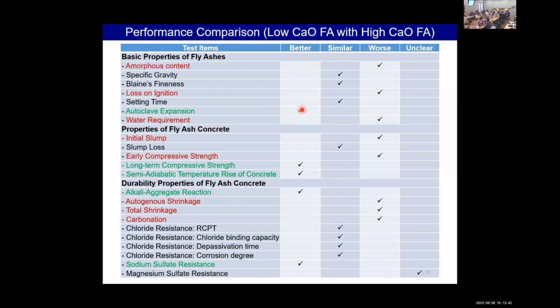For example, if we compare the properties of concrete containing low calcium oxide fly ash, the properties like autoclave expansion, long-term compressive strength, temperature rise, or reaction of the low calcium oxide fly ash are better than the high calcium oxide fly ash. Some properties are similar, but some are worse.